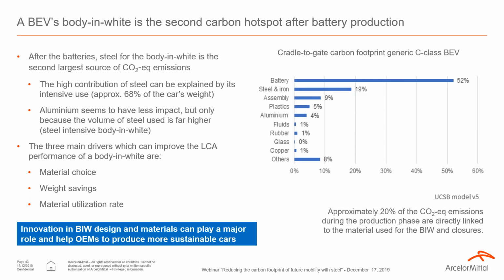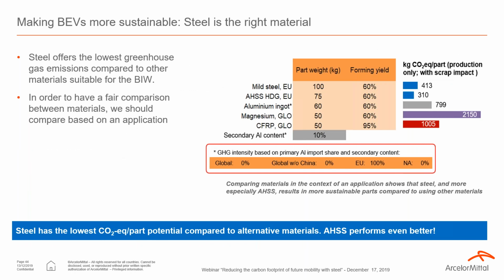There are 3 points which would help the car manufacturers to reduce the CO2 equivalent emission of their cars. So first of all, which material should be used in a body in white? Of course, it depends on the application, and it's very complicated today to bring an overall picture, but we think that we can work on a generic approach where we take into account the mechanical properties of the materials and also the forming yield of the material. So it means that for stamping, for example, we have to trim the part, whereas for some plastic injection we can have a very high yield because here we have no scrap.